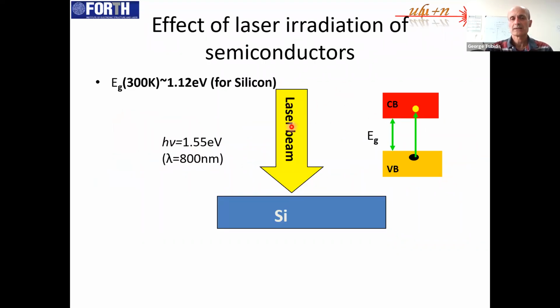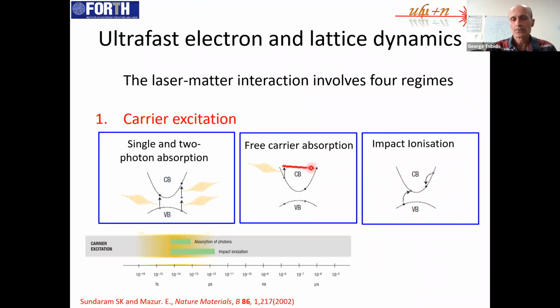Since we are interested in investigating the response of the semiconducting system, we know that for semiconductors, there is a band gap. So when we want to excite electrons, we have the valence band and the conduction band. So it is important that the photon energy of the laser beam we use be significant so that the electrons can reach the conduction band. With respect to this, we have to be a bit careful because there are some processes that can facilitate this excitation. So with respect to the carrier excitation, I have sketched here what happens.